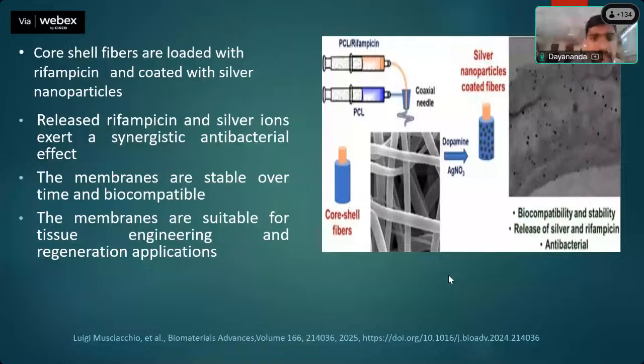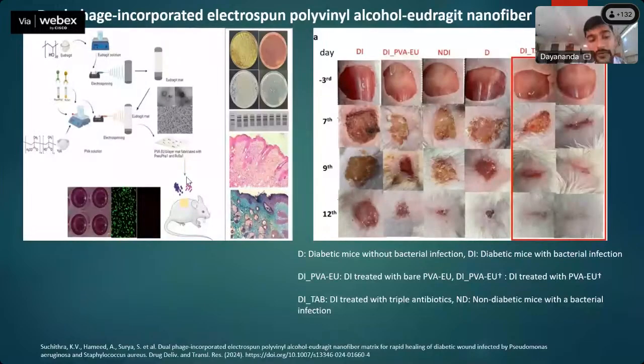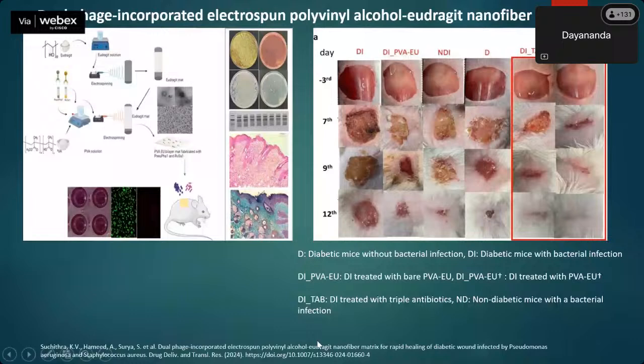This was another nanofiber mat that I had fabricated, with a strategized structure. Initially we used a base material - we took PVA as the base material. As the upper layer, we used Eudragit, in which we incorporated bacteriophage. This work was published, and the fabrication part I had done, and it was evaluated for diabetic wound healing. It was noteworthy that the fabricated nanofiber mat showed improved efficiency in wound healing ability compared to existing work.